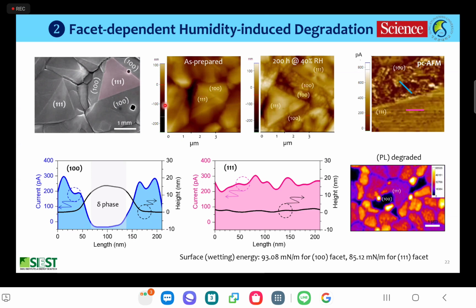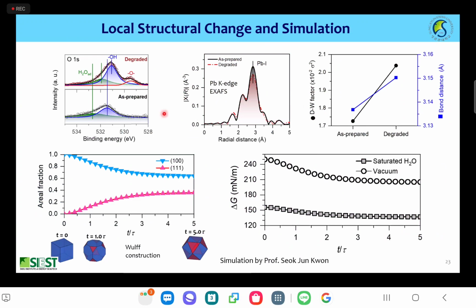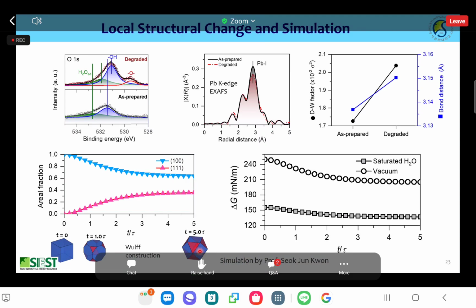We were also interested in the moisture stability depending on crystal facet, because there is some surface energy difference and also some polarity difference depending on the crystal facet. Interestingly, we found that the 100 crystal facet is weak against moisture intrusion. However, the 111 crystal facet is quite stable under moisture conditions. This is due to the delta phase formation of the 100 crystal facet under moisture conditions. The local structure, XPS and EXAFS studies confirmed that the degradation product is related to the delta phase. And by calculation, we also found that over time the 111 crystal facet seems to be quite stable compared to the 100 crystal facet.